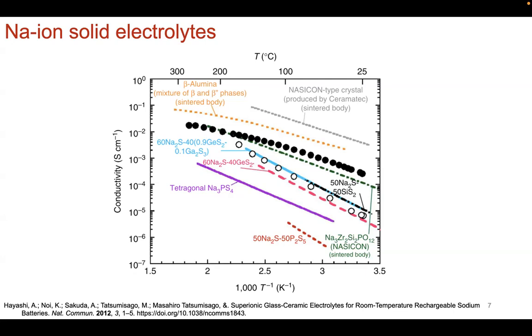And what we've seen for lithium ion solid electrolytes is just that. We've seen liquid phase synthesis with Li2S and P2S5 stirred in tetrahydrofuran. We've seen microwave assisted synthesis, basically rapidly heating. We've also seen quenching to arrest the metastable phase. So we can employ the same methodologies for sodium ion solid electrolytes as well to study their behavior and properties, but really try to correlate the structure to the properties that we observe. And there are a lot of interesting studies that have come out looking at how the local structure really dictates what you observe macroscopically in terms of the ionic conductivity.